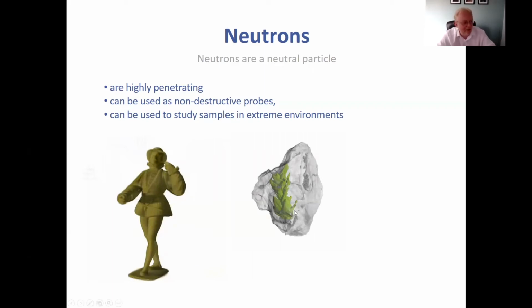So a particular way that that works is you see this rock, this siliceous piece of material. You can see inside there's this green leaf. If you do a neutron experiment, this is actually neutron tomography imaging of a rock. You see the organic matter very clearly because it contains carbon and hydrogen, which scatters neutrons very strongly. Whereas the siliceous material, the rock material outside it, doesn't scatter neutrons so strongly, and therefore you can see the plant material, which is actually a fossil, within the rock without having to crack the rock open.